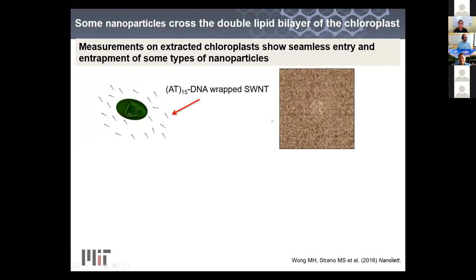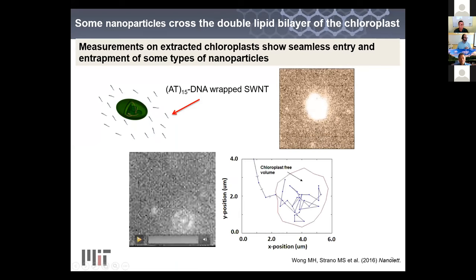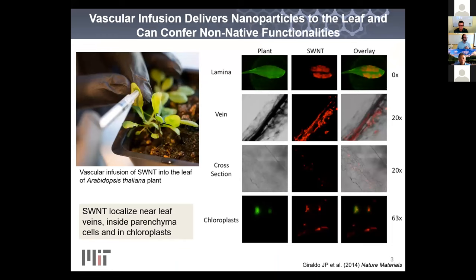Okay, great. So what you're seeing here is actually negatively charged carbon nanotubes that are flowing past and inserting themselves into extracted chloroplast. These chloroplasts have a double lipid bilayer membrane, and on these particles, which fluoresce in the near infrared, you're seeing them make the chloroplast glow. And certain nanoparticles will do this spontaneously. So they don't have to be attached to a viral capsid. They have it as a part of their chemistry.